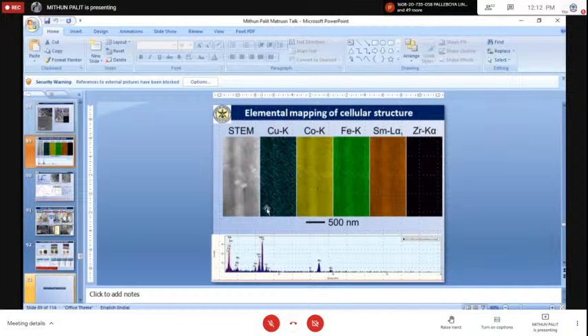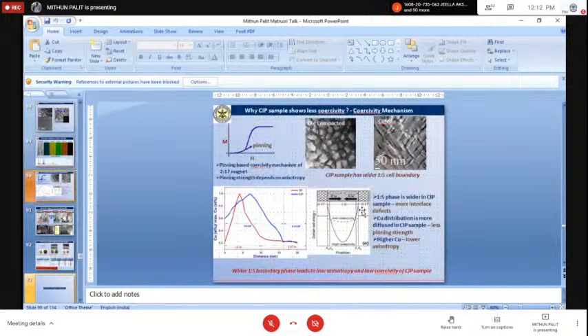You can see that in the precipitate phase there is more copper but less iron, whereas in the matrix phase, I don't know at this magnification whether you are able to see because it's not going to full screen. However, I tell you that this precipitate phase has more copper and less iron, and the matrix phase has less copper but more iron. But then this precipitate wall width is different in the two samples. A conventionally processed material has a very thin width, and a CIP processed material has a wider width.